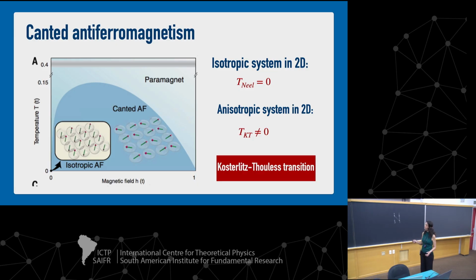And this is a cartoon of what is happening. When we have no polarization, we have an isotropic system. But when we put this magnetic field, what we see is that the spins are canted. They prefer to lay on the plane than to be perpendicular to the plane. And this is an anisotropic system in 2D. And because of this anisotropy, we can have a non-zero critical temperature. And this is very interesting for experiments.